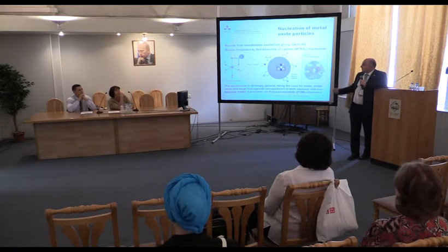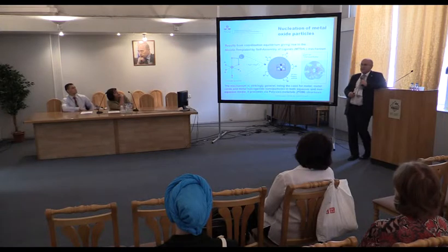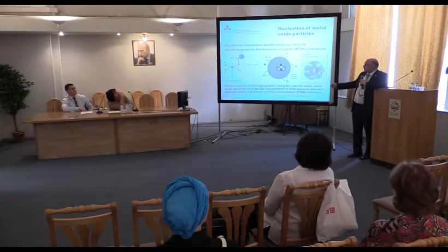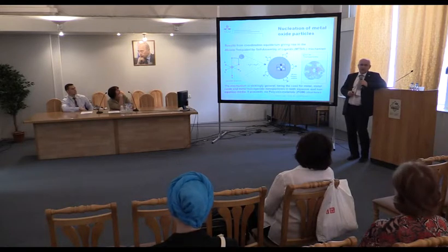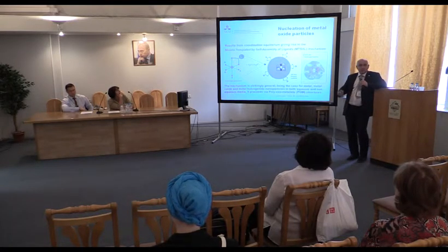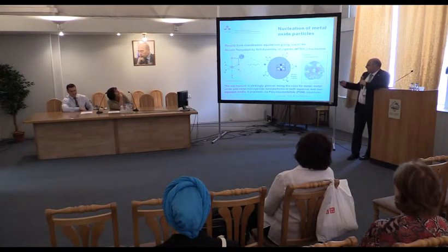So what we can conclude is that everything that is happening on the way from individual metal organic precursors into primary particles in sol-gel, of course it is hydrolysis, polycondensation, but it is leading to core structures which are densely packed of cations and anions, and in the core they can be crystalline. I will show you an example when these particles already are crystalline. You can see the X-ray diffraction from them. And they are covered by residual organic ligands.